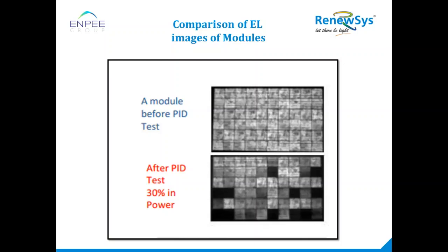Okay, noted. Thanks, Sandeep. Another question that has come in is with regards to encapsulant. Can using POE instead of EVA make any difference? Yes, the general term the industry uses is POE. I said polyolefin; polyolefin is POE only. Polyolefin definitely has a higher dielectric strength compared to the EVA we generally use in the solar industry. Yes, it is going to help a lot in terms of PID if you go for polyolefins.